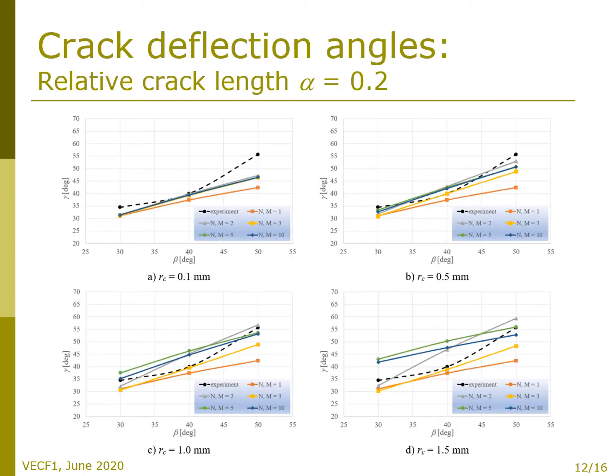Finally, you can see the results of the crack deflection angles obtained. The first slide corresponds to short cracks with their relative length of 0.2. You can see dependencies of the initial kink angle gamma on the crack inclination angle beta. Comparison between experimental results, dashed line, and results obtained via GMTS criterion considering various numbers of the initial terms of the Williams expansion, n and m, was equal to 1, 2, 3, 5, and 10.